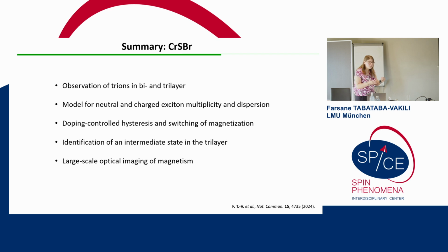And so with that, I want to summarize by saying that we've observed trions in bi- and trilayer chromium sulfur bromide for the first time. In the meantime, at least 2 other groups have reproduced these results. We've developed a model for the neutral and charged exciton multiplicity and dispersions, and we've shown doping-controlled hysteresis and switching of the magnetization, as well as identified an intermediate state in the trilayer, and we've shown large-scale optical imaging of the magnetism. This work was just published in Nature Communications about a month ago.